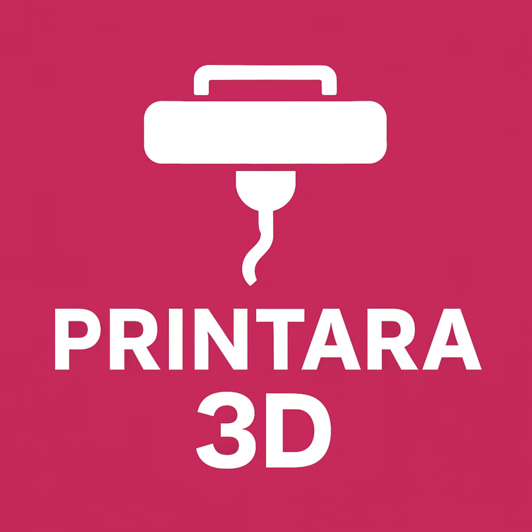And there is a vital geometry rule to add to this. For any flat base over roughly 100 square centimeters, you really need to use a 5 to 10 millimeter brim. A brim is a thin, single-layer skirt of plastic printed around the perimeter of the object, physically attached to the first layer. It acts like a massive suction cup. Exactly. It dramatically increases the surface area in contact with the bed.